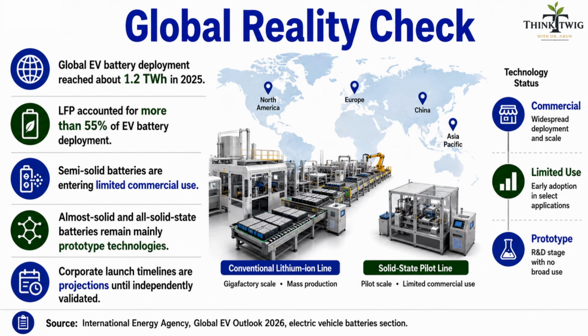Now look at the global market. It is moving fast. According to the IEA, global EV battery deployment reached about 1.2 terawatt hours in 2025, and that was nearly 30% higher than in 2024. At the same time, LFP batteries become even more important. LFP means lithium iron phosphate, and it accounted for more than 55% of global EV battery deployment. Why is that important? Because LFP is already cheaper, already commercial, already improving, and relatively thermally stable.